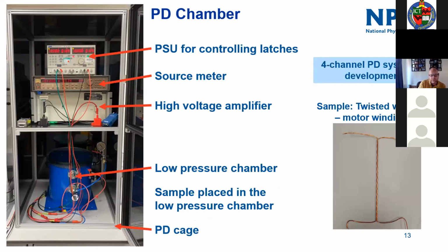So we have built this single channel system at the moment, which involves an amplifier system which can go to 5 kilovolts, a vacuum chamber here which we can take down to about 0.1 bar with appropriate pass-throughs. We're also measuring simultaneously the insulation resistance of the system, because we want to understand how that insulation resistance drops off as we age the system, age the materials within the system. And what's not shown here for some reason is the waveform generator.